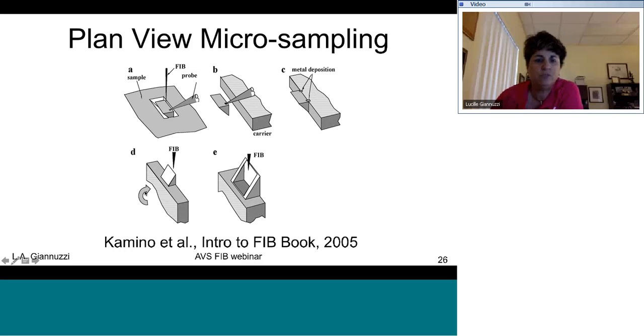And now you have to flip this up. So there are some stages that can do this inside of the FIB. If you don't have a special stage or substage, you have to break vacuum, flip the carrier or grid then upright so that you can FIB mill at any plane now parallel to that original surface. All right.